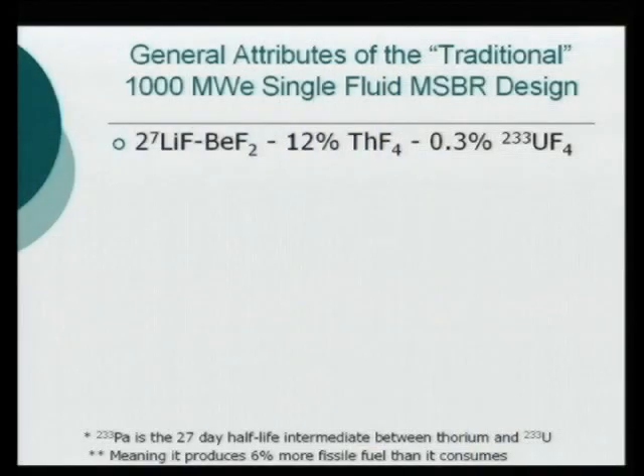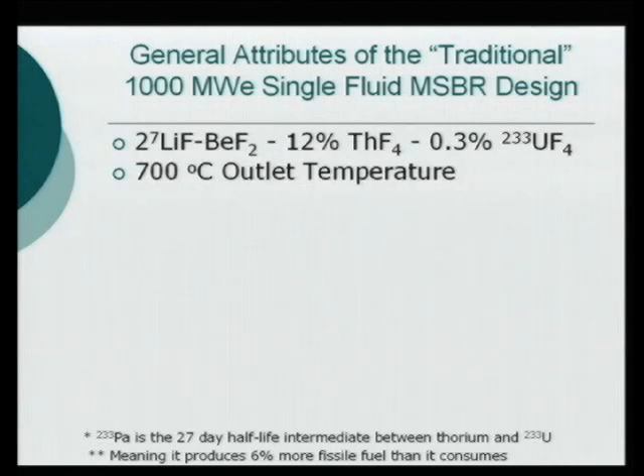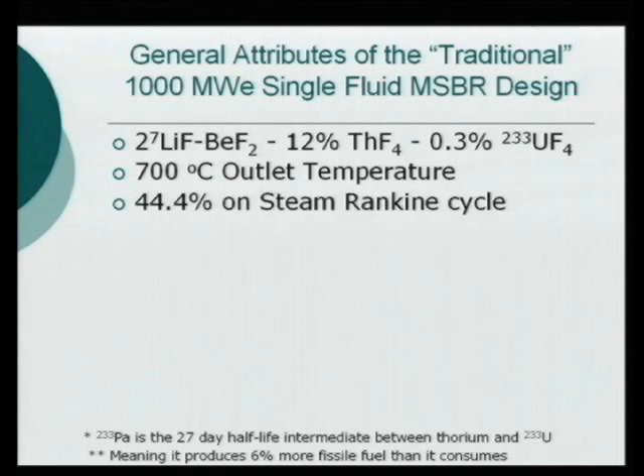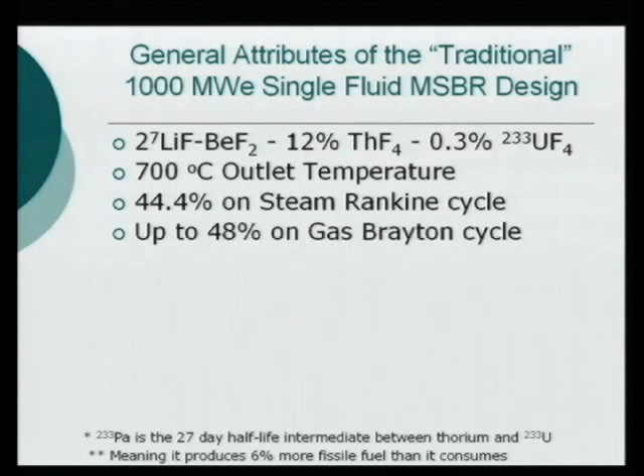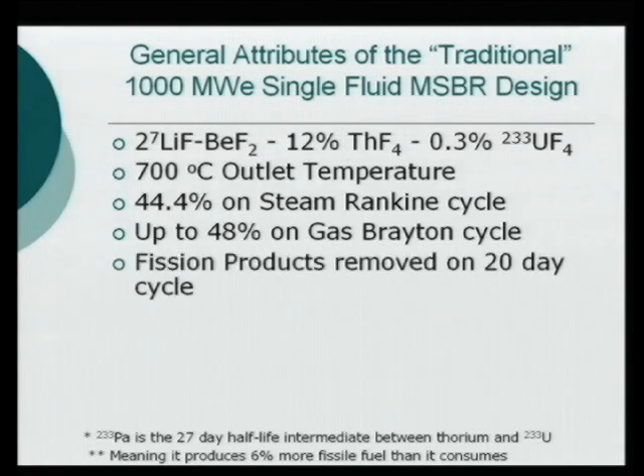So, the general attributes of this traditional design, called a molten salt: you have a salt that dissolves a mixture of, in this case, the fertile thorium fluoride and uranium fluoride mixed in a carrier salt that's lithium fluoride and beryllium fluoride. And that lithium has to be isotopically enriched, which makes it a little expensive, but not too bad. It has a nice high outlet temperature of 700 degrees, so we have a nice high thermal efficiency. Oak Ridge work was over 44% on the steam Rankine cycle. If we switch to a gas Brayton cycle, like helium or even supercritical carbon dioxide, we can get up to the high 40s. The fission products in this case were removed on a 20-day cycle.